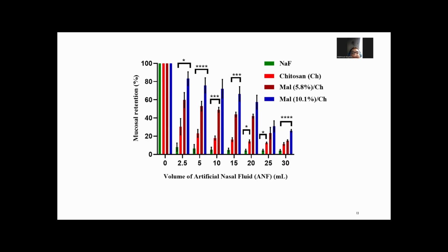With the software, I can analyze the data about mucosal retention. At 0 time, all of them are 100%. But after washing with 2.5 ml until 30 ml, the mucosal retention decreases, but the maleimide, the blue column, is still high from the start until the end. After washing with 30 ml of artificial nasal fluid, it still retains about 25 percent. For chitosan it is very, very low, like 5%, but maleimide is still high.